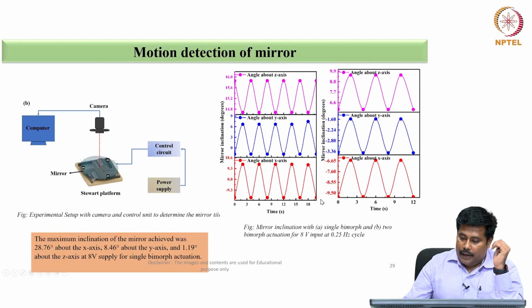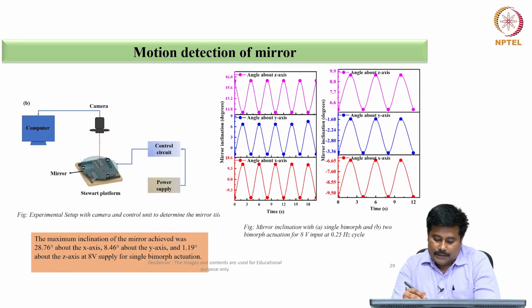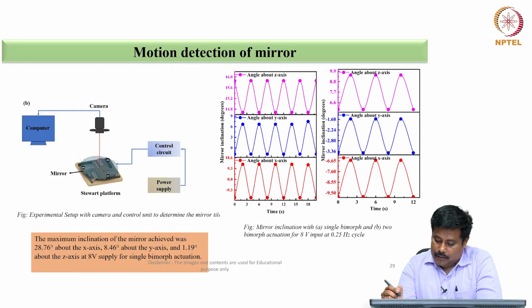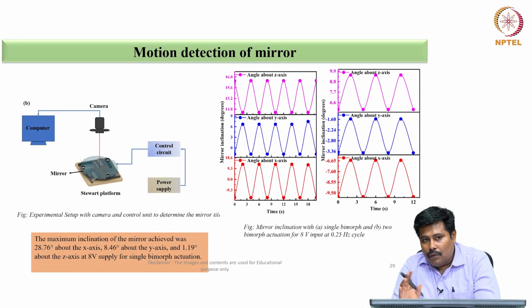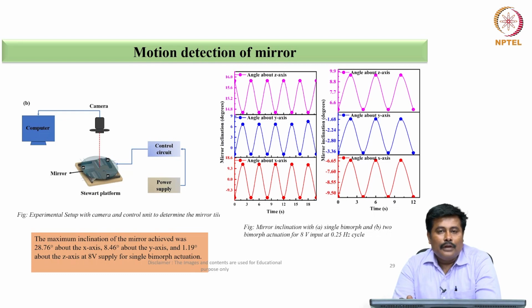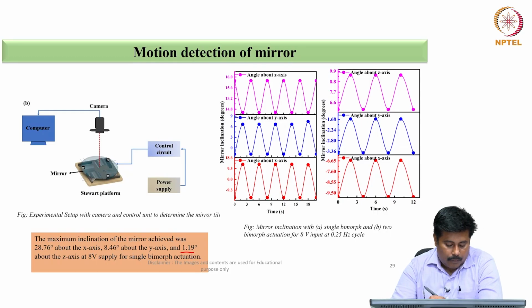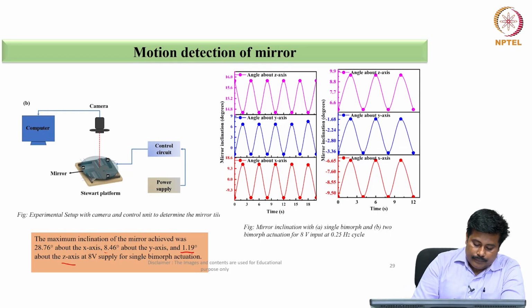Okay, so if you see the overall response of this, it is a micron inclination which has been observed. In this micron inclination, the overall system is designed in such a way that the maximum inclination of the mirror achieved was close to around 28.76 degrees about the x-axis, around 8.46 degrees about the y-axis, and around 1.19 degrees about the z-axis.